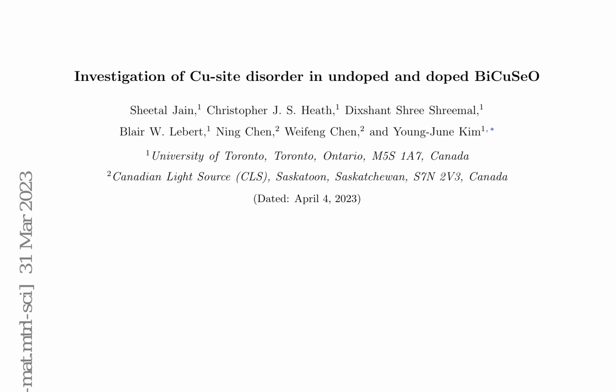This suggests that the void surrounding the Cu site is substantial, accommodating the larger Ag1+ ion without necessitating lattice expansion, supporting the concept of a rattling mode at the Cu site in BiCuSeO. Ag doping further decreases lattice thermal conductivity in both single and dual-doped samples. To understand the origin of this suppression, it is essential to address the dopant site issue. While Pb is generally accepted to replace Bi in the BiCuSeO framework, as confirmed by XANES measurements, the dopant site for Ag has been debated.